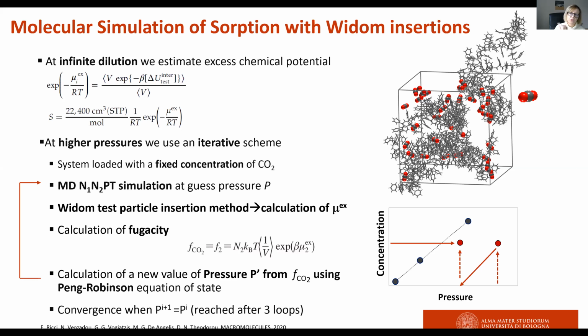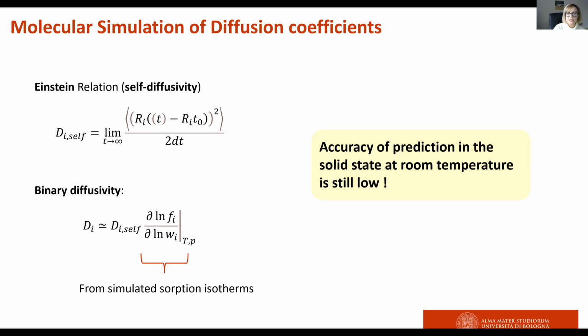If you are at higher pressure, you have to insert your CO2 molecule into a polymer loaded already with CO2 molecules. And this is, of course, necessary to predict solubility isotherm. And in this case, you have to apply an iterative scheme to exactly match the external gas pressure with the equilibrium amount of CO2 in the membrane. But the convergence is reached after only 2 or 3 loops of the iteration. Einstein relation is the one normally used to predict the self-diffusivity, and of course, to predict the mutual diffusivity, you need a sorption isotherm, as we explained in the previous slides.